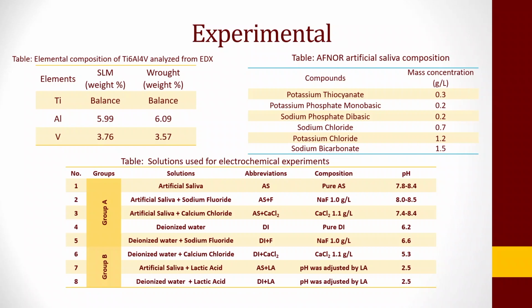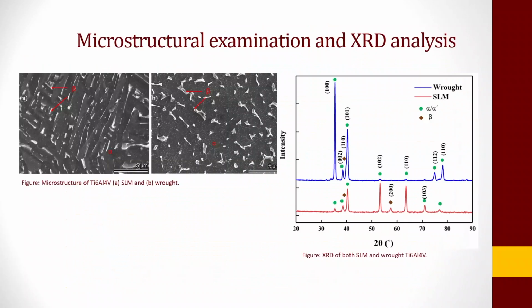And this artificial saliva has different types of compounds, as you can see, and their mass concentration is given as well. Now, we have made different types of solutions, because we added, let's say, sodium fluoride into the artificial saliva and made one type of solution. And then we added, let's say, calcium chloride into artificial saliva and made another type of solution. Then we have the original or pure artificial saliva. We do have deionized water, and we did use lactic acid and artificial saliva, and also lactic acid and deionized water, to see the effect of different compounds on the electrochemical and the other properties of titanium, aluminum, vanadium.